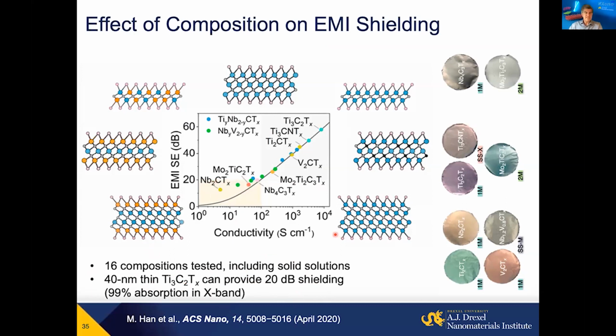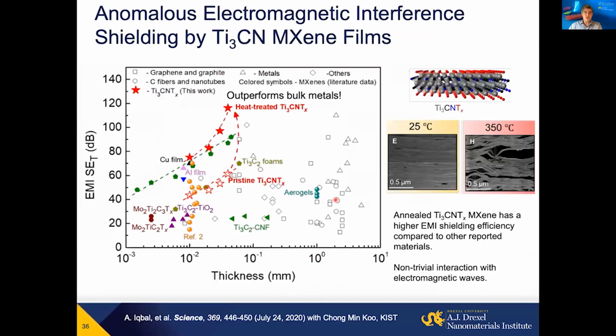And of course, depending on their conductivity, they show different performances, but it's also changing non-linearly. So there's a lot of interesting science we're trying to figure out. And just about 2 months ago, we published another paper with Chong-Min Koo, actually really breaking all the records and showing that titanium carbonitride MXene, which is actually less conducting than titanium carbide Ti3C2 MXene, outperforms even copper films. And with very thin films, it's possible to achieve enormous, virtually complete absorption and reflection of electromagnetic waves.